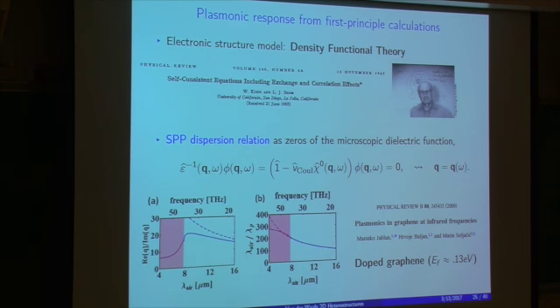We have the total field, phi, out of which we subtract the reaction of the material, create some charges. Out of these charges, we can extract what is the potential created by these charges. And so now we have subtracted out of the total field what the reaction of the material creates. If this reaction is 0, then that means we do not have to apply any external fields for this disturbance to exist. This is the definition of a resonance. So if we find the zeros of this dielectric function, which can be computed from the DFT, then we will identify the plasmonic response of the material.